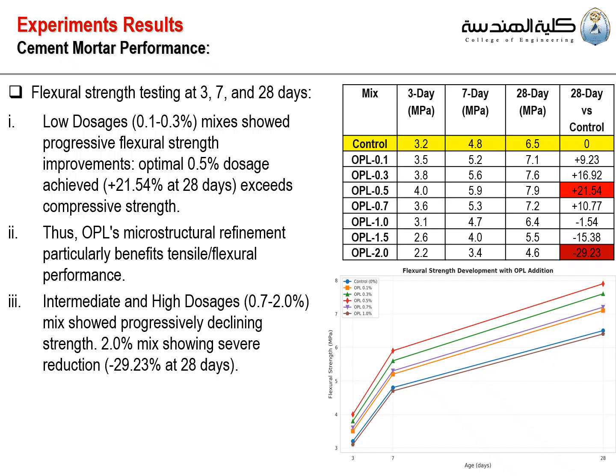The intermediate and high dosages from 0.7 to 2 have shown declining strength, where we have a severe reduction, negative 29.23% at 28 days with the OPL 2% mix.